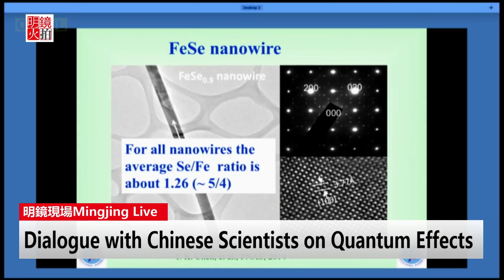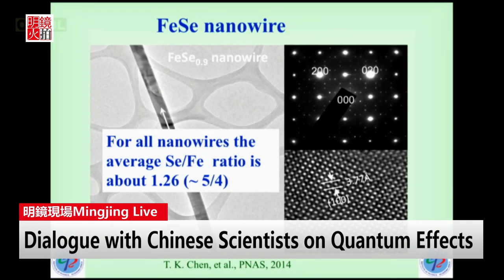And we identified something quite interesting: the ratio between selenium and iron is 5:4, which means 4 iron with 5 selenium. But if you look at the original picture I showed you, it should ideally be 1:1. But why is this 5:4? And that gives you a very interesting, beautiful superstructure from the X-ray and the electron diffraction.